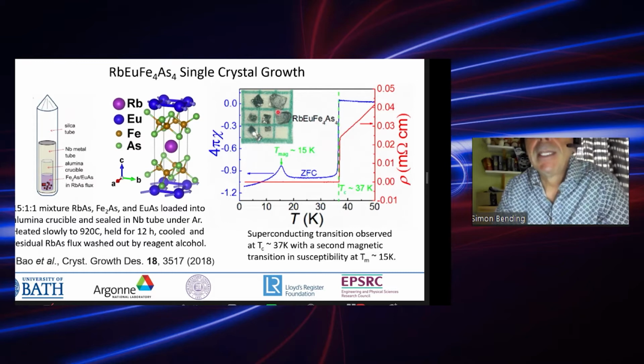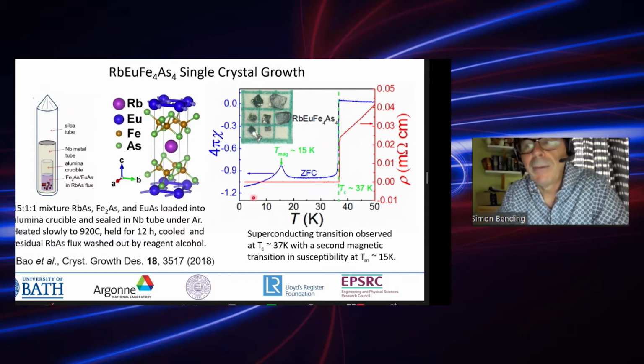So we end up by doing that with these very nice platelet-like crystals, which have nice flat, shiny surfaces, which is perfect for scanning probe microscopy. If we want to study then the superconducting property of these crystals, we can, for example, look at the resistivity as a function of temperature. That's the red data here.